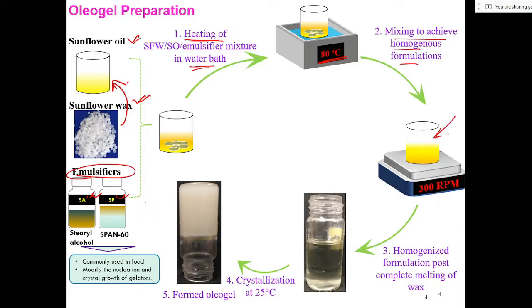We mixed it to achieve a homogeneous solution, so we got a homogeneous solution. We homogenized it at 300 rpm on a magnetic stirrer, and then we kept it for crystallization at 25 degrees centigrade to form oleogels. So this is the final oleogel that we got. Okay.